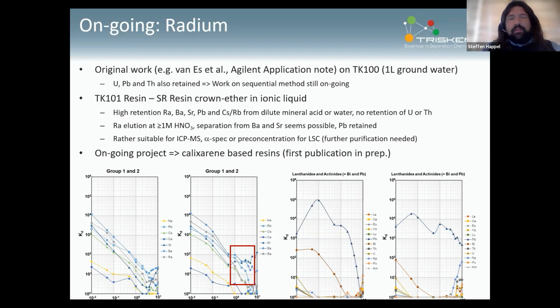So we are working quite a lot right now on calixarene-based resins that should have much higher selectivity for radium over these elements, particularly radium and barium selectivity. So in the ideal case, we would like to be able to switch, keep the barium or remove the barium, either to use it as internal standard or to remove it to have a high purity radium fraction.